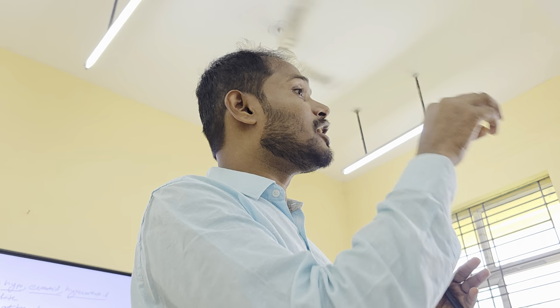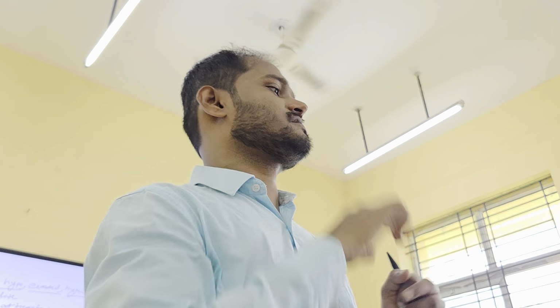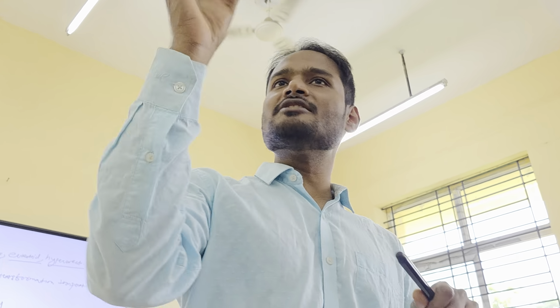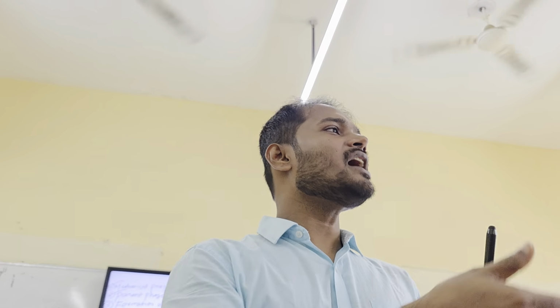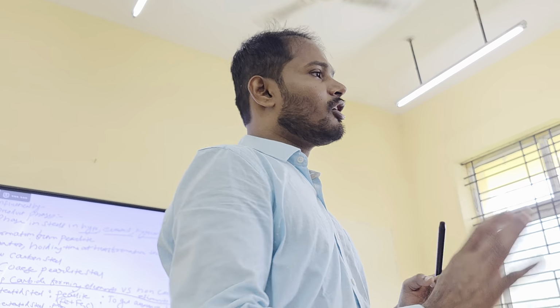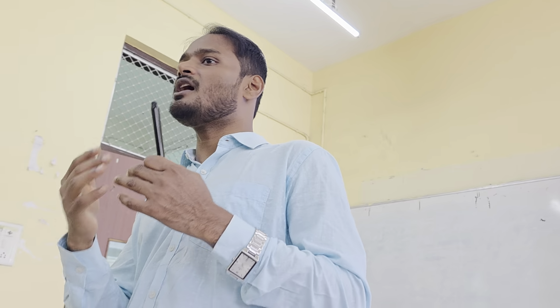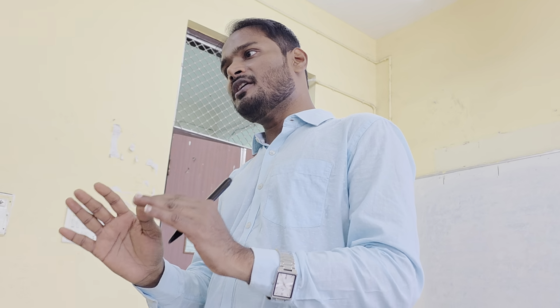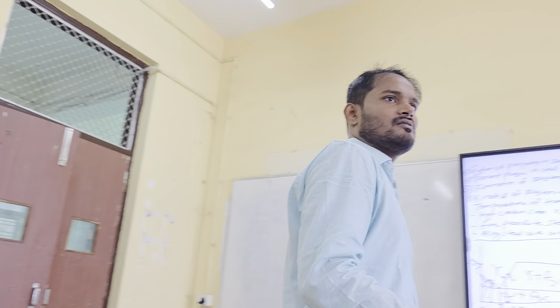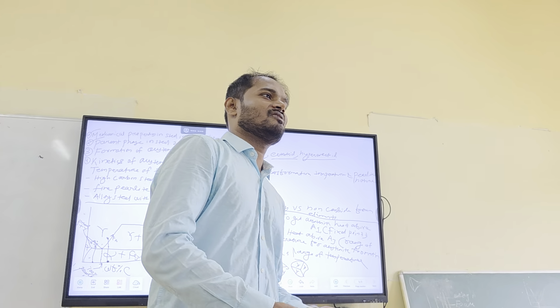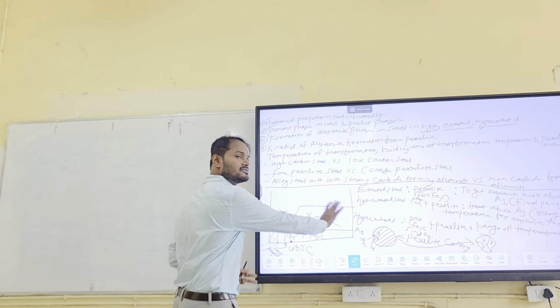Some nucleation may happen along the grain boundary of the proeutectoid phases. Do you understand now? Right? Because that is also a grain boundary, and a grain boundary is a high energy region. So nucleation can easily occur. Most of the nucleation always occurs along the grain boundaries, because grain boundaries are high energy. Energy is already available for the nucleation. I mean driving force is available, you can say. Okay. So this is done.